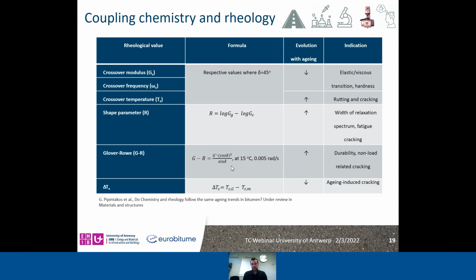With regard to the rheological parameters that were extracted from the master curves, I will just show in brief here in this table. One can extract different crossover values which have an indication, for example, for cracking. Also the shape parameter R, which is actually the logarithmic difference between the glassy modulus and the crossover modulus, can give us some indication about fatigue cracking. All these values, of course, have a clear evolution with aging according to literature. And finally, some of the most prominent values that are used nowadays for scientific purposes are the Glover-Rowe parameter and the delta Tc value, which are related to non-load related cracking and aging-induced cracking. The formulas and the relations of them are given.